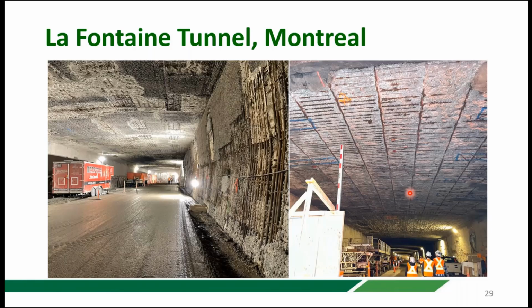Down inside the tunnel, here you can see a couple of images. You can see, obviously after the roadway is removed, and the tiling from the walls was removed, and they've done some surface preparation. It's not in the greatest of condition, and all of the issue here is chloride-induced corrosion because of salt spray, because of the cars and trucks going through here, just create a salt mist in the air that settles on all the surfaces.